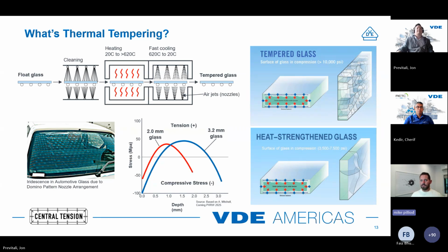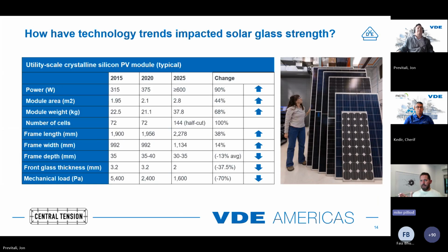So I think for our purposes, going to 2 millimeters, you end up not being able to induce enough compressive stress in the surface, and that depth of layer is a function of your thickness. So 20% of 2 millimeters is less deep into the glass than 20% of 3.2 millimeters into the glass.